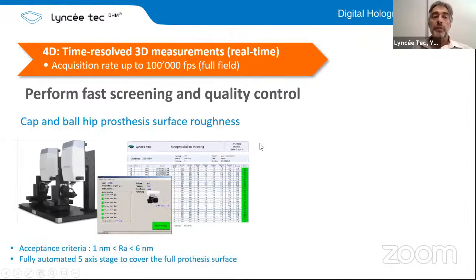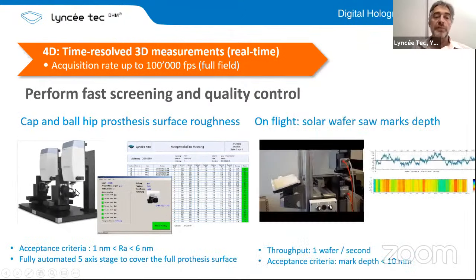We can also perform fast quality control. This is roughness quality control on hip prosthesis. So basically, we have automated rotation. This is for both cap and ball for prosthesis, which have roughness over the full surface between 1 and 6 nanometer. And this is the case when we make on-flight quality control of saw marks on wafer.